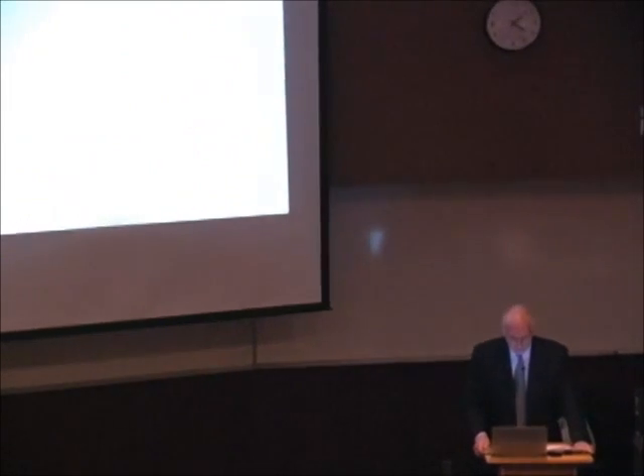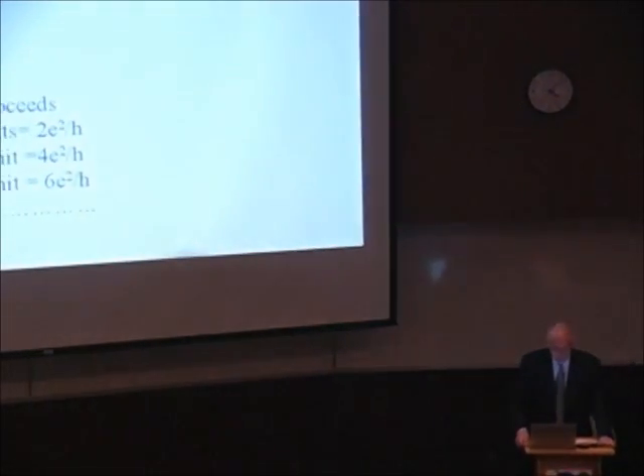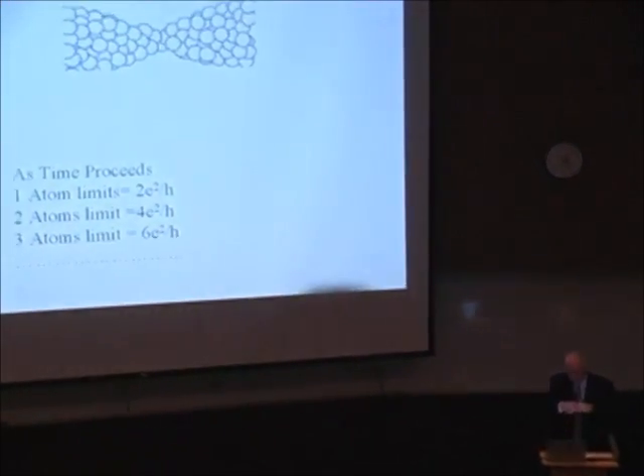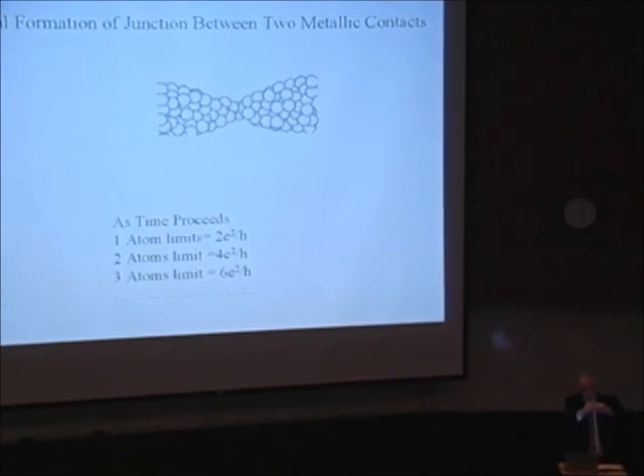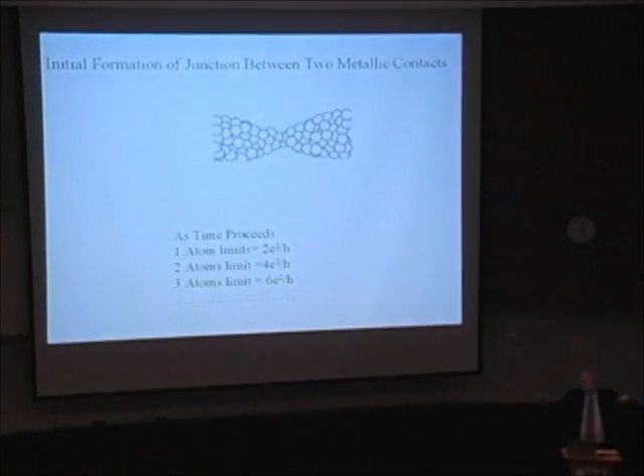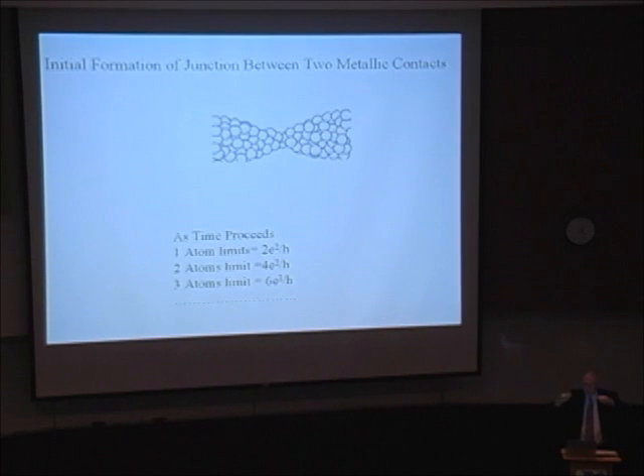Now, there are many other examples of how one can actually get a quantized conductance. Not necessarily at low temperatures either. For example, if one takes a regular metal wire and we just stretch it like that, it will of course break. If we measure the resistance as it breaks, the resistance gets higher and higher until it goes to a value of infinity because there's no contact.